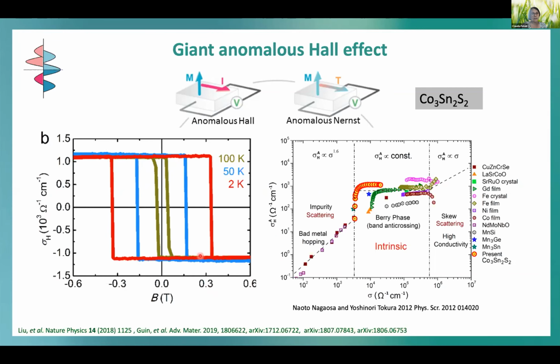We find a large anomalous Hall conductivity in this material, showing a nice big hysteresis because of the hard magnetic behavior. If we put it into the scheme of Nagaosa and Tokura, where they distinguish whether the anomalous Hall conductivity comes from the Berry phase and is really intrinsic, we see that in this material we have a mainly intrinsic contribution to the Berry phase.